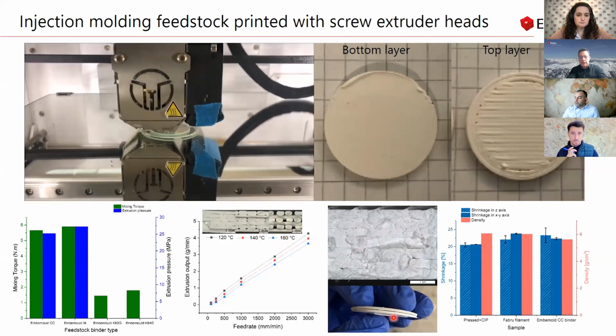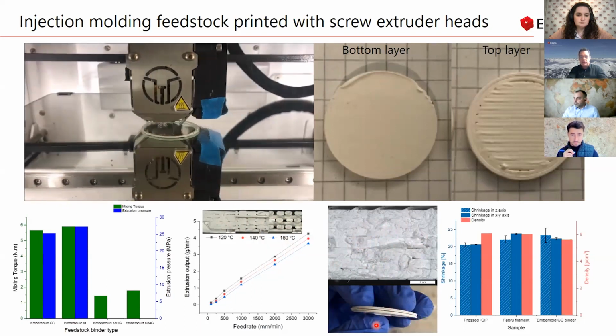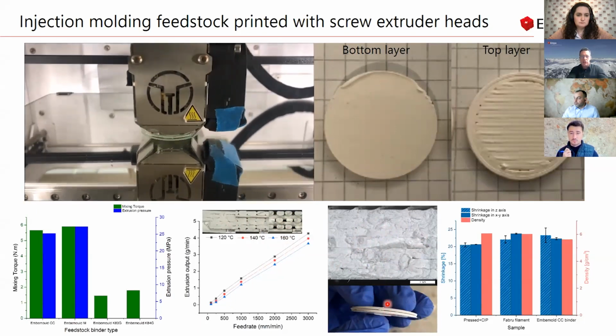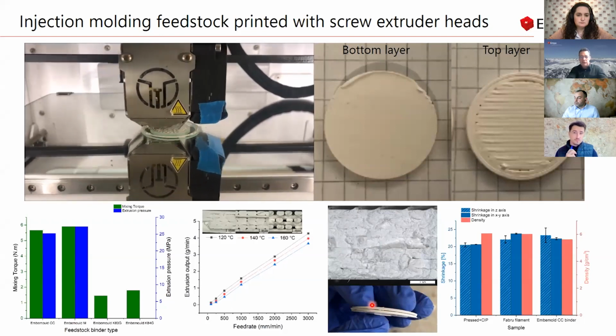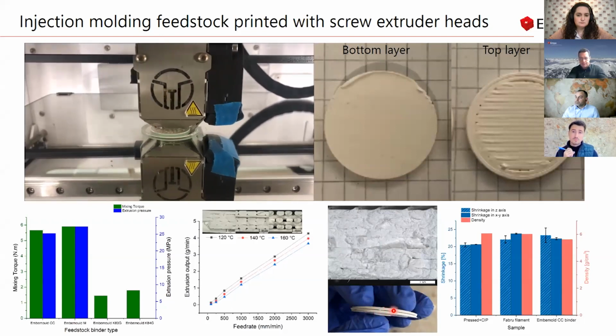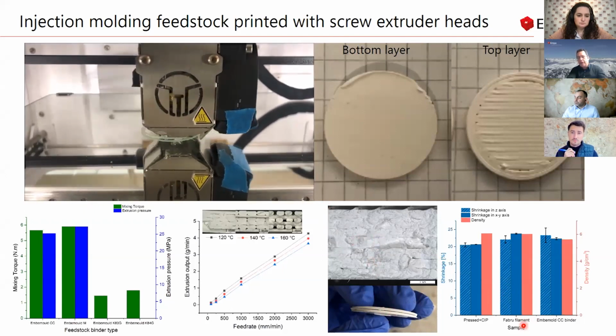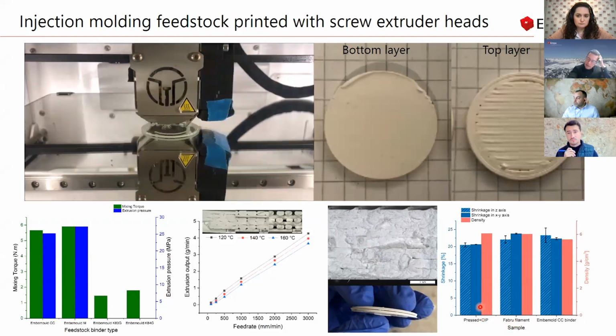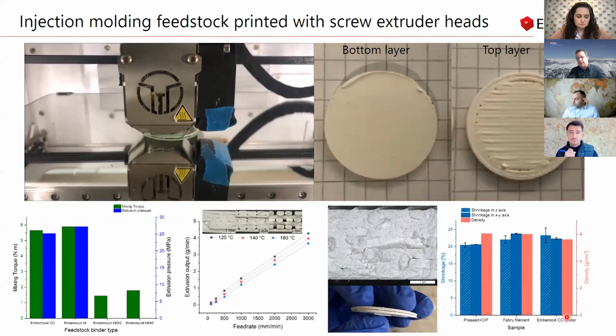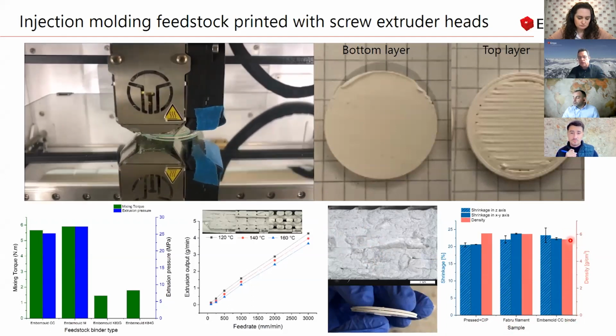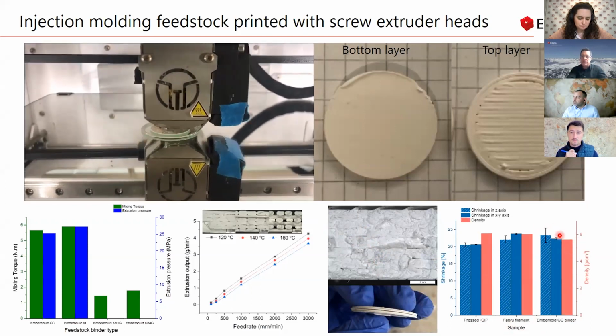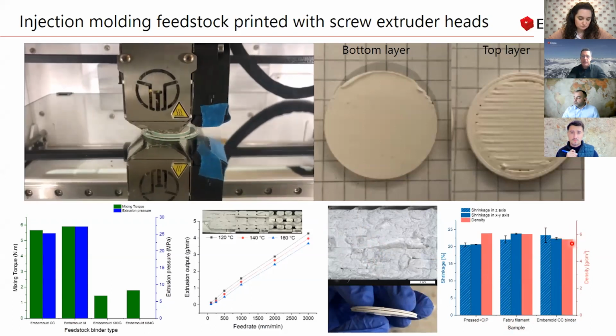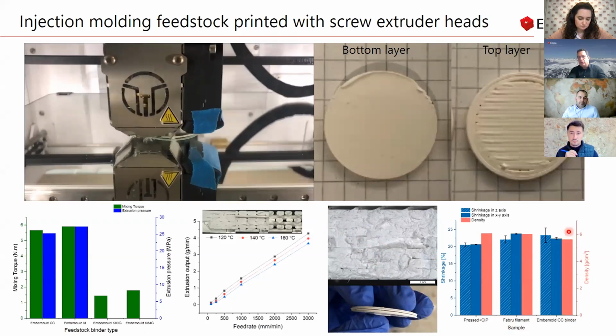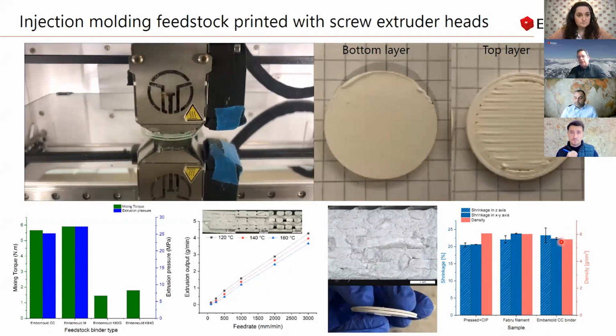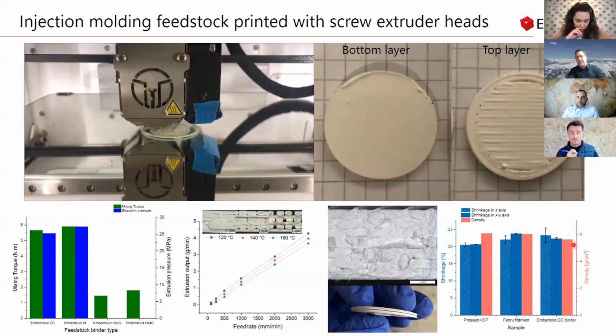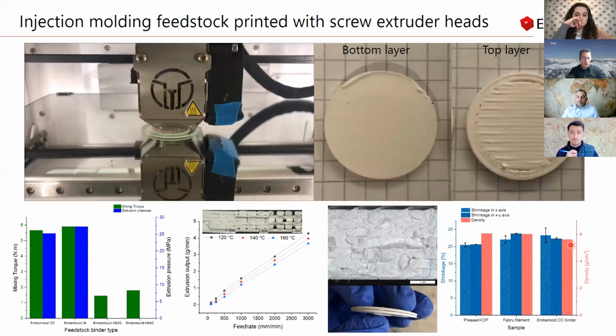One thing you can also see here is that when you do not use the right binder system, you can have delamination. So you really have to test if your feedstock can really be used for 3D printing or not. Another thing we see at the moment when we compare, for example, with filaments, with cold isostatic pressed materials, is that when we go for 3D printing with a screw extruder, we have a lower density, but I think this belongs more to the binder system and not to the printing device itself. So here it's clear that even when you work with an injection molding feedstock, you have to be aware that you probably will not get exactly the same performance as you would expect from your injection molding process.